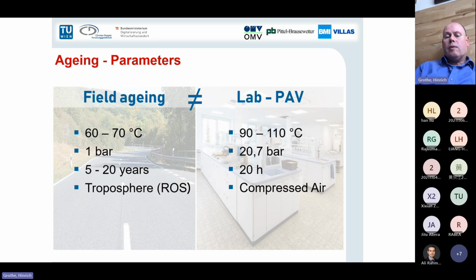And what we try, and not only me, but many groups try to do, is laboratory aging. But laboratory aging, as I want to show you, is different from field aging. What are the differences? Here is a comparison with a so-called pressure aging vessel test. This is a standard aging method. The difference is, first of all, temperature. On a road, you have a maximum of maybe 70 degrees C. But in the pressure aging vessel test, you have 90 to 110 degrees. So the temperature in the laboratory is much higher.